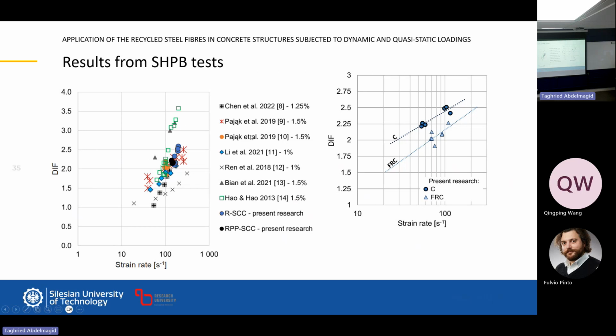And when we compare it with the results from other researchers with the same amount of fibers, this is important because the influence changes according to the amount, and it's not easy to find similar research. We also have to consider the matrix, the compressive strength of the matrix. So these are the results with an exactly comparable matrix and comparable amount of fibers. You can see here that it's very comparable. So it's the same, and the conclusion is that we can use it. In these applications, we have no limits, completely no limits.